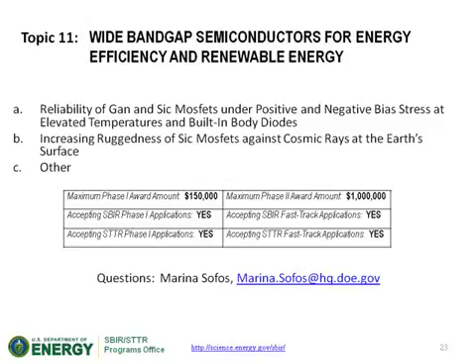So this could include, for example, gallium nitride-based transistors or other device reliability, degradation, and failure concerns that are blocking their scale-up in manufacturing. For subtopic A, the purpose is to fundamentally understand the failure mechanism of commercially available silicon carbide power MOSFETs, which are caused by a large density of interface and bulk traps present in thermally grown gate oxide films, as well as other defects present in the epi layers of silicon carbide, such as threshold voltage shift under application of gate voltage at elevated temperatures.